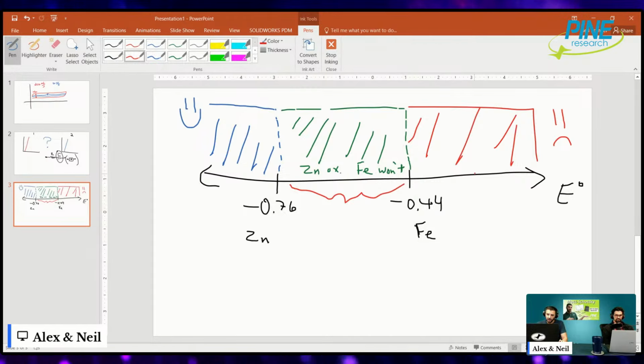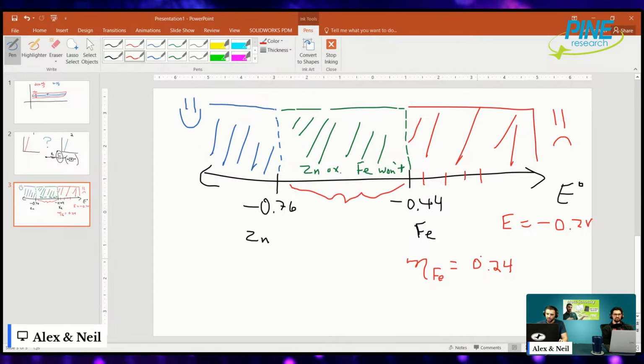The other way to look at that is that if I'm at any potential, the driving force for zinc is greater than the driving force for iron. So whatever the potential happens to be, if the potential is equal to minus 0.2 volts, that means that my overpotential for iron oxidation is 0.24 volts, right? Did I do the math right? However, the overpotential for zinc oxidation is bigger, right? It's 0.56.